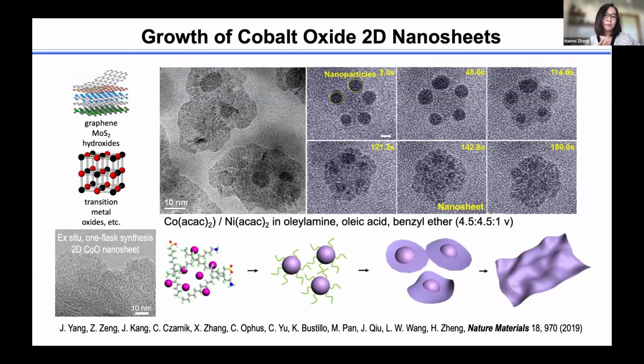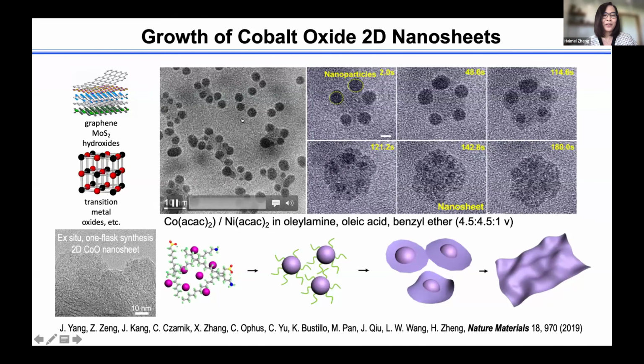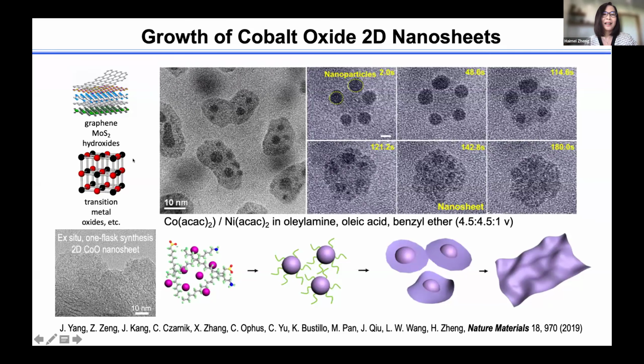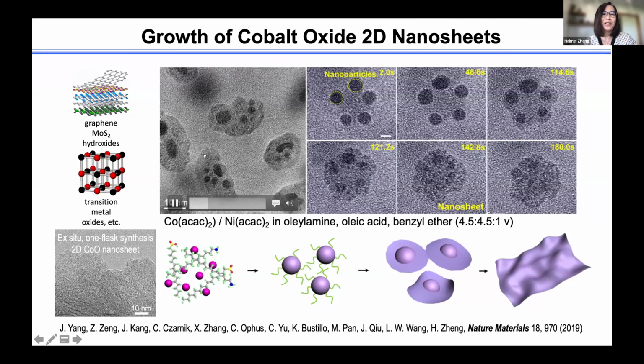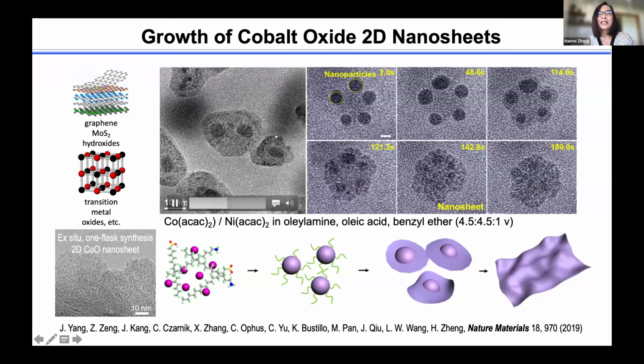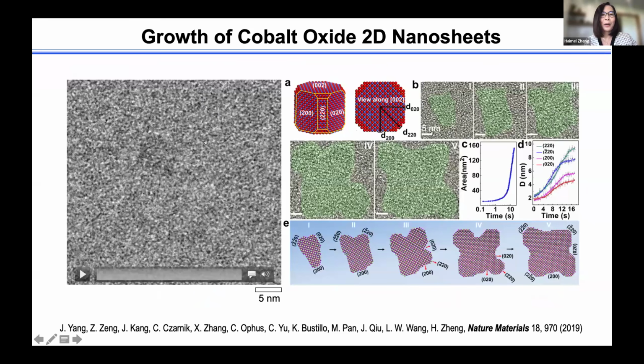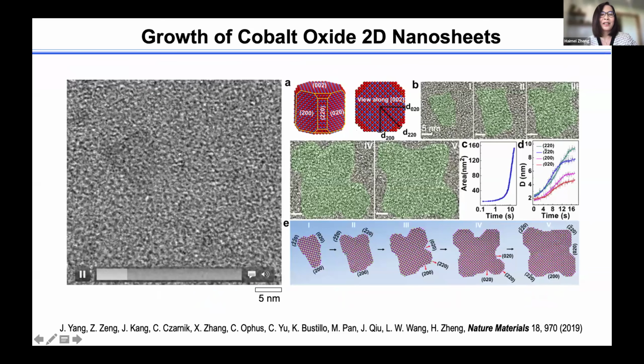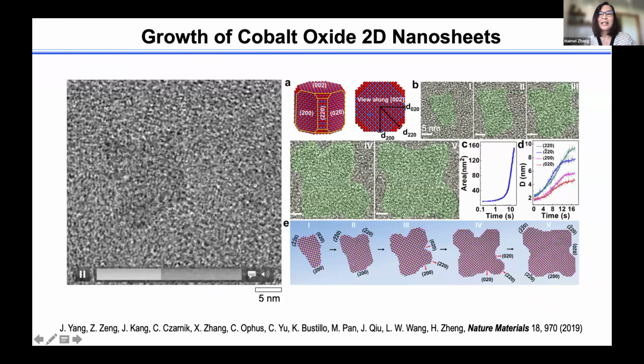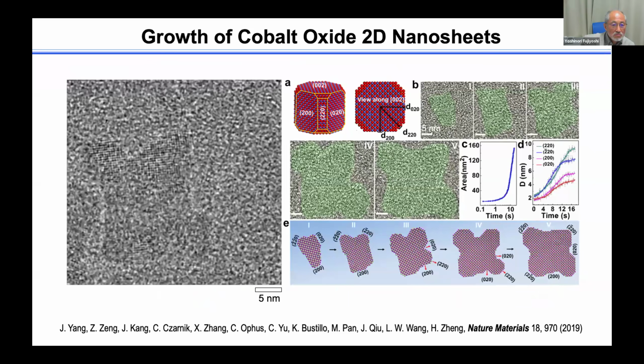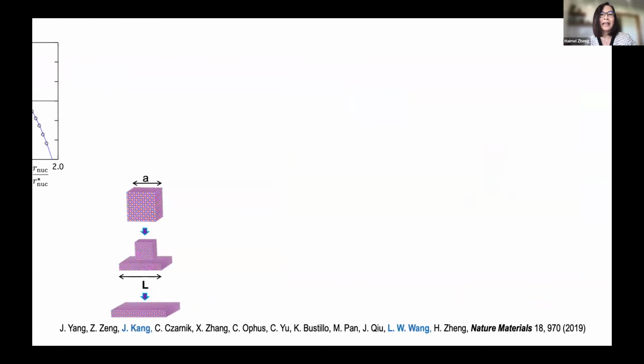However, cobalt oxide has cubic structure. But the system showing this 2D nanosheet growth is counterintuitive. We mostly look at this type of growth, and we found using this molecular precursor in the liquid cell, we formed this nucleation of nanoparticles first, and then they transform into 2D when they grow into certain size. And this is very interesting. We look at more detail and use a higher resolution, many different movies, and they show this 2D type of growth.